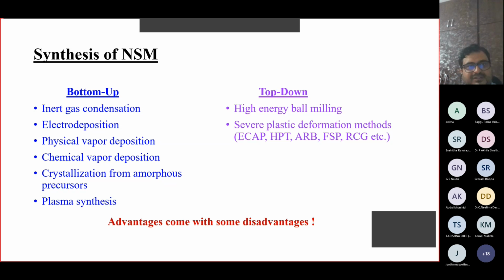In the bottom-up approach, you really can make very small grain size and really small materials. You can also make thin films and highly pure materials, but you cannot make larger samples. Whereas using the top-down approach, you can make reasonably larger samples, but the grain size limit that you can achieve has some constraints. You cannot make as small a grain size as you have realized in the bottom-up approach. And further, you have impurities that come into the top-down approach. So therefore, the advantages that one technique offers cannot be offered by other techniques. Therefore, I made a philosophical statement here that advantages come with some kind of disadvantages in the adoption of these processes.